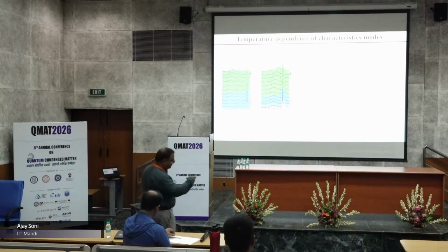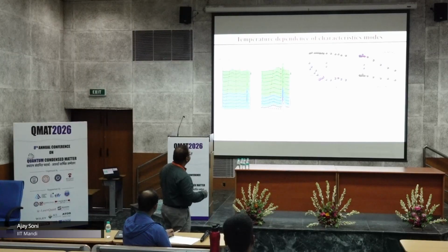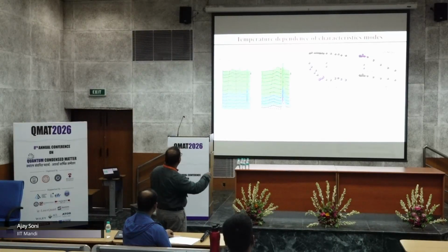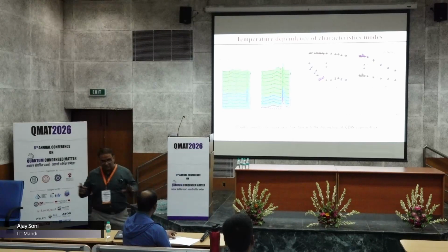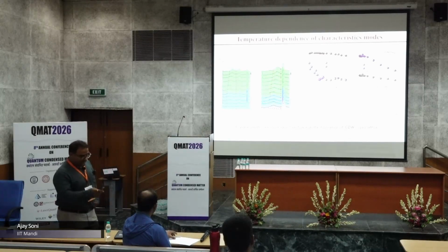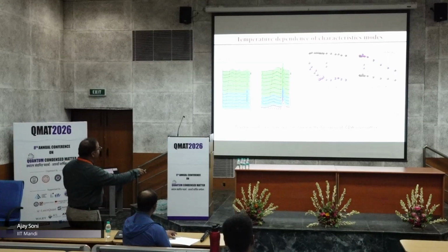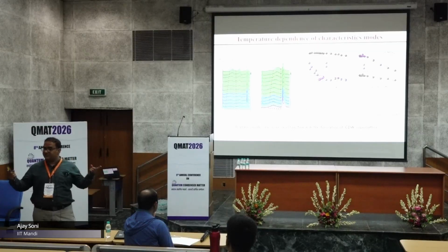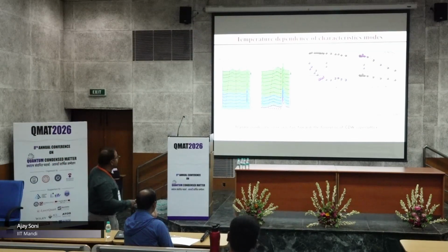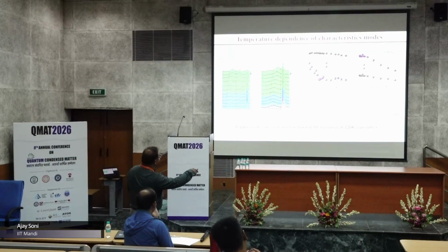So we understand it from the temperature dependent Raman spectra. From the temperature dependent Raman spectra, you can estimate from the anharmonic model that if the red curve is following the data, that means it is a harmonic behavior, okay, and if there is a deviation from that, that actually tells us there are some interactions, and we call that the electron-phonon interactions, which are leading to the instabilities in these materials, and that is happening exactly at the charge density wave transitions.